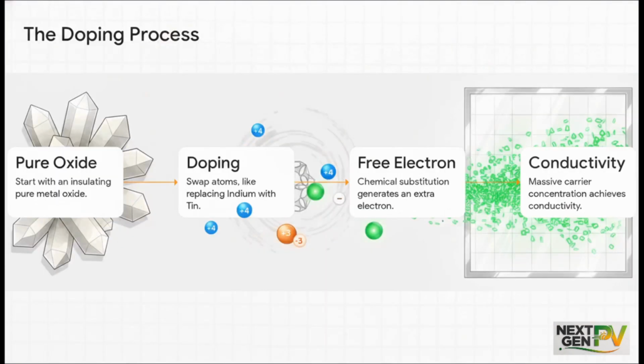But remember, pure oxides are insulators. We still need this stuff to conduct electricity. We do this through a process called doping. Let's use indium tin oxide, or ITO, as our example. Engineers start with the insulating oxide and they introduce doping. Specifically, they swap out an indium atom, which has a 3+ charge, with a tin atom, which has a 4+ charge. That tiny calculated chemical substitution physically generates a free extra electron. You multiply that across the entire material and you achieve a massive carrier concentration. That gives you metallic-like conductivity right inside what is basically a transparent window.